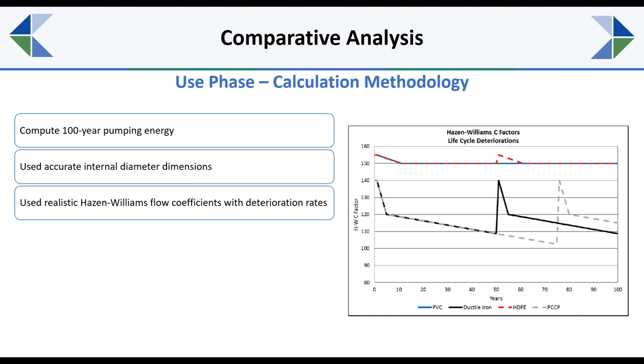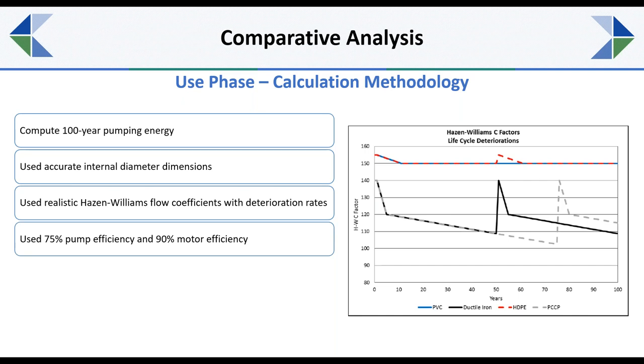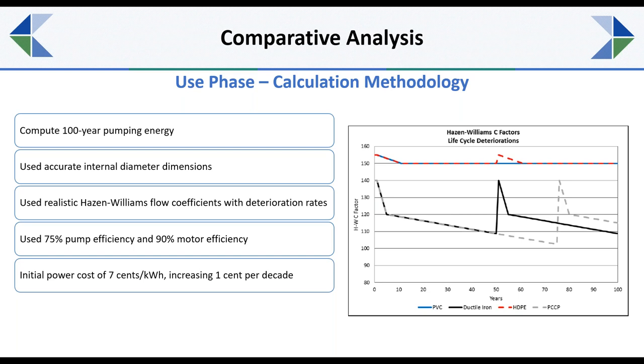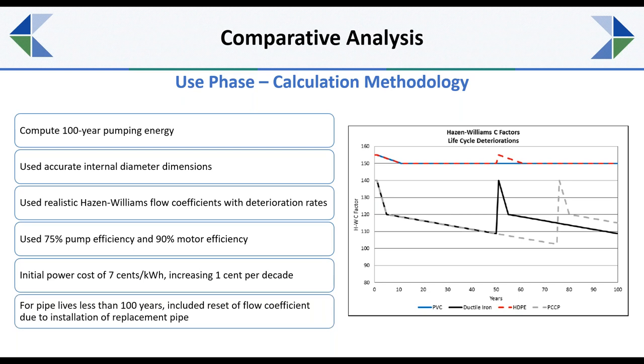The jumps in the graph actually show where you would need to replace the pipe, and it actually ends up improving the flow coefficients when you've replaced the pipe. We use 75% pump efficiency and 90% motor efficiency, and we assume some standard initial power costs and escalation over time. So any pipes that were rated to be less than 100 years in lifespan, we included the reset of those flow coefficients.